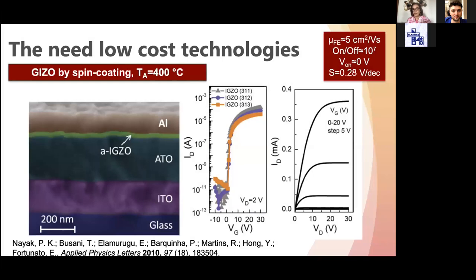Also, this is another example of some spin-coated devices. So here we have indium gallium zinc oxide. So we are mimicking what is used by the industry in terms of the high-performance TFTs. And here we have a high-resolution cross-section of a TFT, where you can identify all the layers. For example, the green one, this very thin layer of some tens of nanometers, is based on amorphous indium gallium zinc oxide. This is also to tell you that besides the low cost of these materials, the amount of material that we need to use is very, very thin. It is just some tens of nanometers.